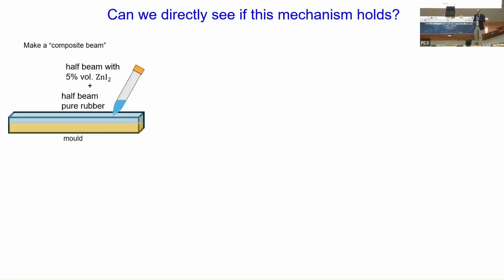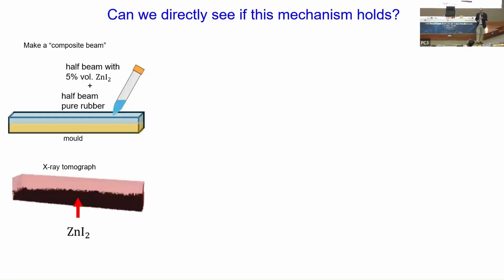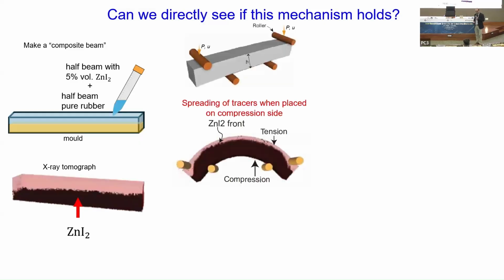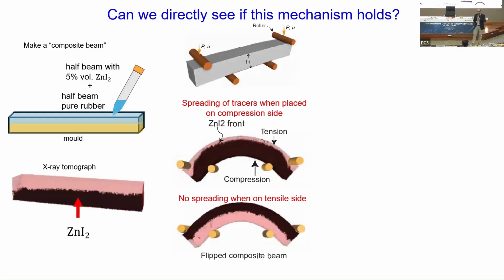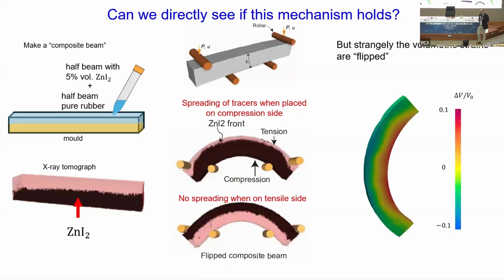Okay, so if I look at this beam, this is what I've made up. I do this experiment, and this is what happened. What you can see is that all this black stuff which was sitting at the bottom has moved to the top, the minute you do a compression experiment. When you do a tension experiment, you can see that it all remains on the same side. It doesn't really move at all. So this has proved to us that there's something moving inside this material.